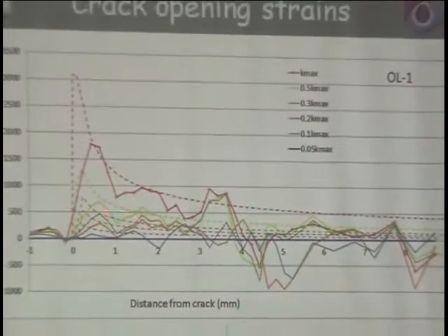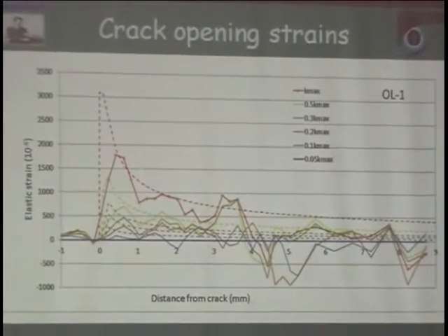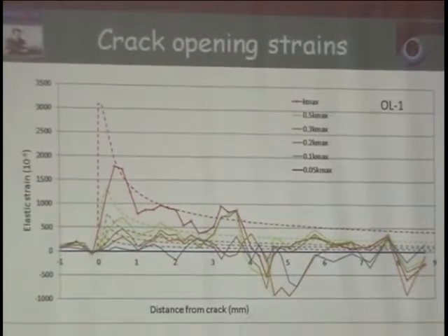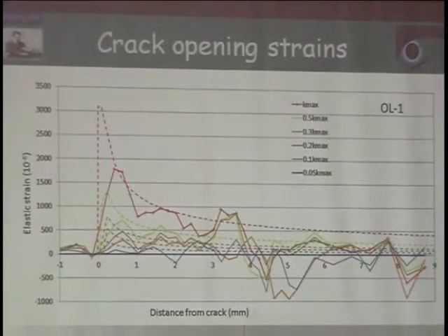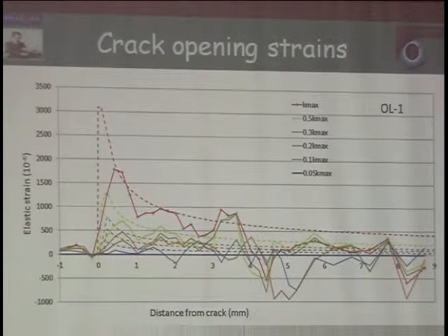And you can see the curves are more or less elastic, but that the peak here is not being fully realised in the real case. Whether that's due to smearing or whether that's a real effect is perhaps open to debate. On top of that, you see lots and lots of scatter, and that's due to the crystallite grain size.